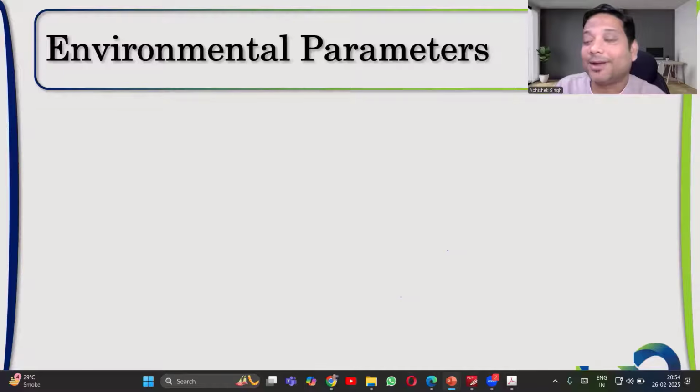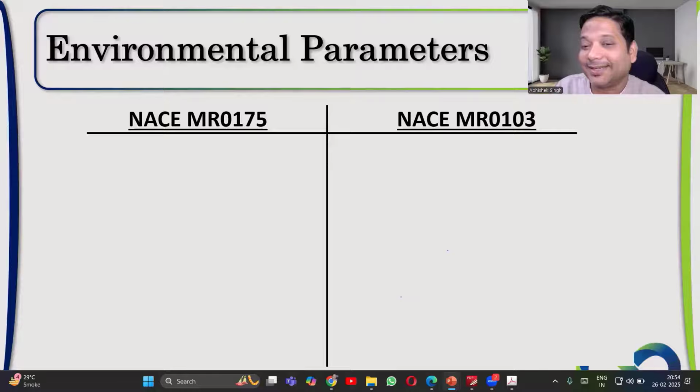What about environmental differences? Can anyone tell me? When I say environmental, I'm considering the partial pressure of H2S. You spoke about 0.3 kPa, right? At 0.3 kPa NACE 0175 becomes applicable.